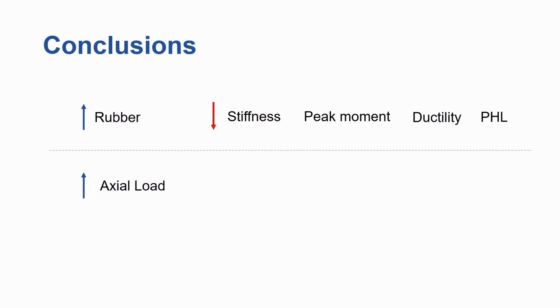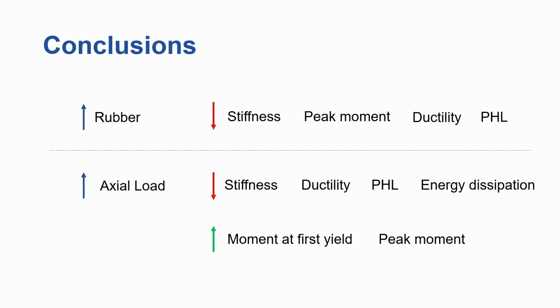So to finish this off, as the rubber content in the concrete infill increases, at least for the case of the square steel tubes, we do see a reduction in stiffness and peak moment, which was expected from the beginning. But the other thing we did not expect is a reduction in ductility and plastic hinge length, indicating that the rubberized concrete didn't help that much for the case of the concrete filled specimens. And then for the axial load levels considered in this study, there is a reduction in stiffness, ductility, plastic hinge length, and energy dissipation, and an increase in moment at first yield and peak moment.